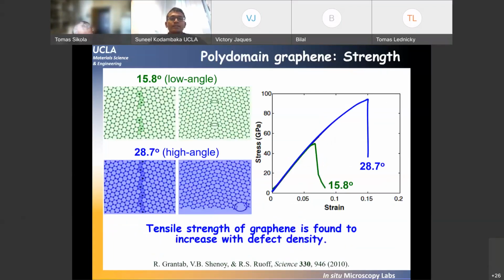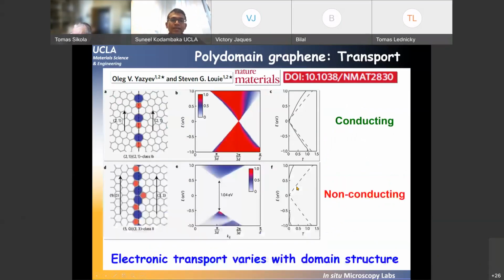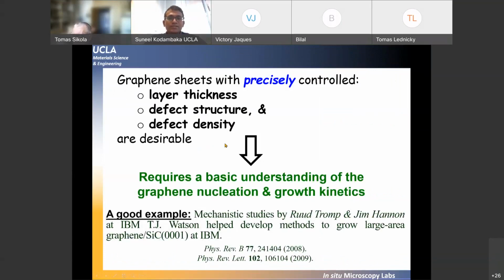And more importantly, people have studied how defects influence either mechanical or electronic properties. Here is one atomistic simulation that shows that the type of defects within a 2D layer, in this case graphene, affects the mechanical behavior of the graphene. And electronically as well, depending on the type of defects, you can have a perfectly conducting domain boundary or an insulating domain boundary. So the electron transport across these domains depends on the type of defects and domains that you have within a monolayer graphene as well. And experimentally, this has been verified too. So basically, all these studies indicate, as you probably know, that defects are important. One needs to be able to control, and if needed, eliminate these defects completely.